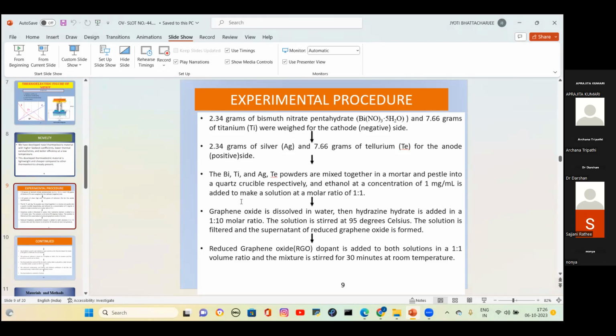I have to make reduced graphene oxide. So for making reduced graphene oxide, I first dissolved graphene oxide in water and then I added hydrazine hydrate as a reducing agent in 1:10 molar ratio at 95 degrees Celsius. Then after that, I have added the reduced graphene oxide as a dopant in both the solutions in 1:1 volume ratio and have stirred it for 30 minutes at room temperature.